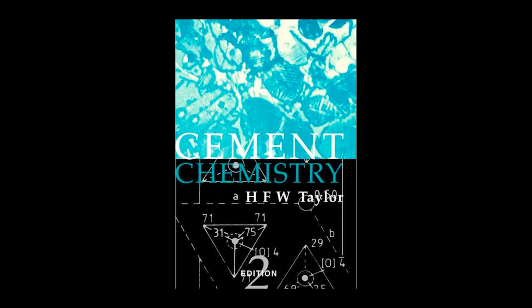That makes perfect sense. So it's not just a barrier. It's the solution struggling to accumulate the necessary chemical density. This combined theory is a really beautiful piece of kinetic modeling. It is. And the low rate of dissolution during the induction period can really only be explained if the concentration gradient of these ions near the grain surface is extremely high, which supports the idea that that initial product layer is really doing something to slow the release of material. It's chemical patience being rewarded with structural growth.